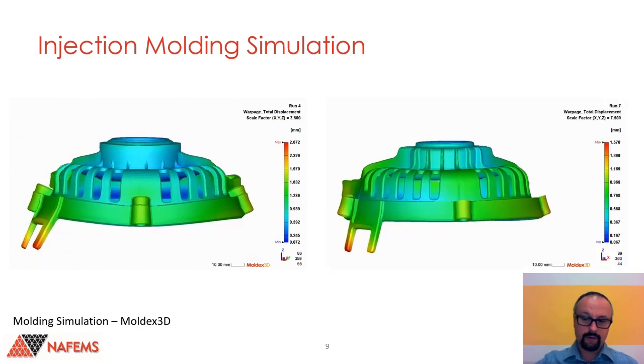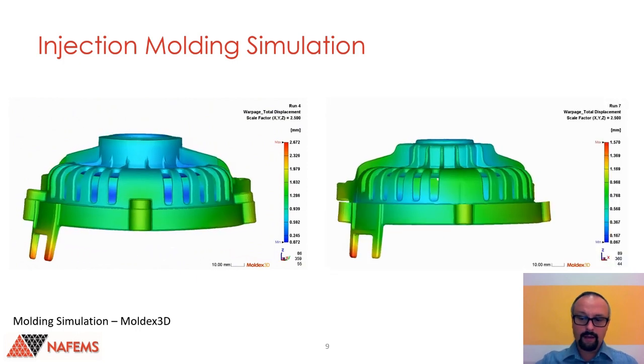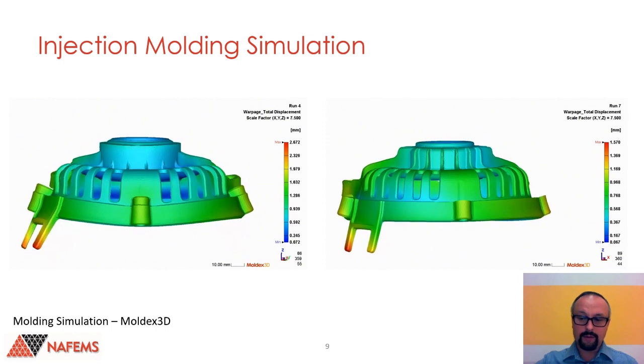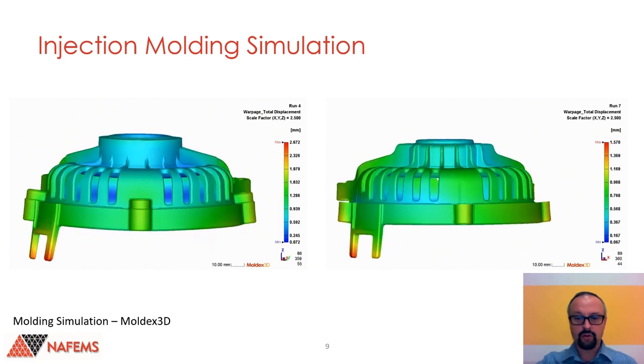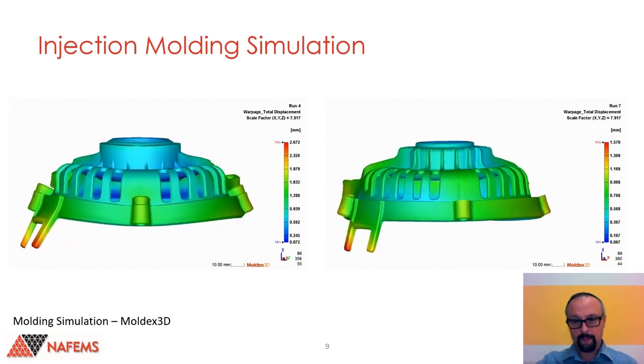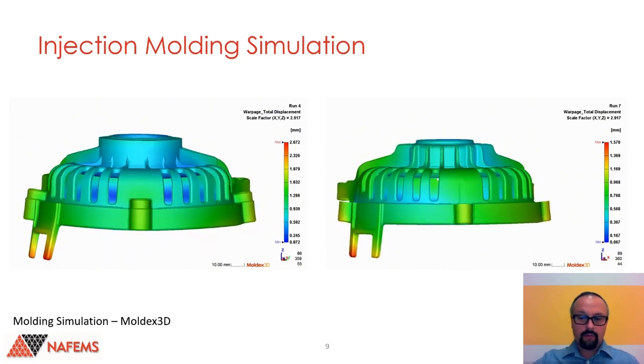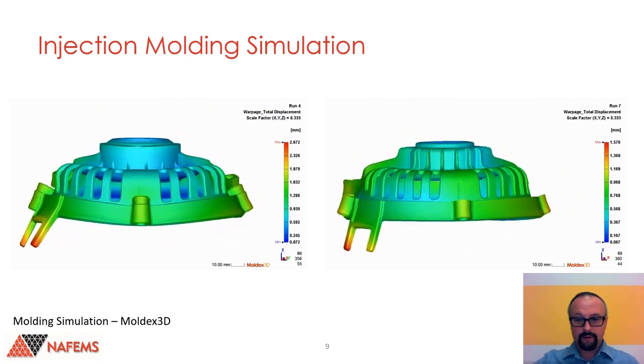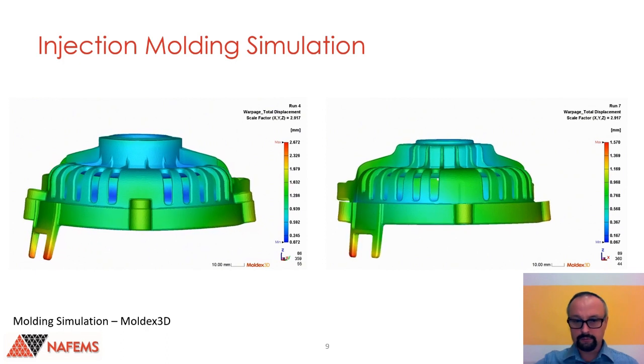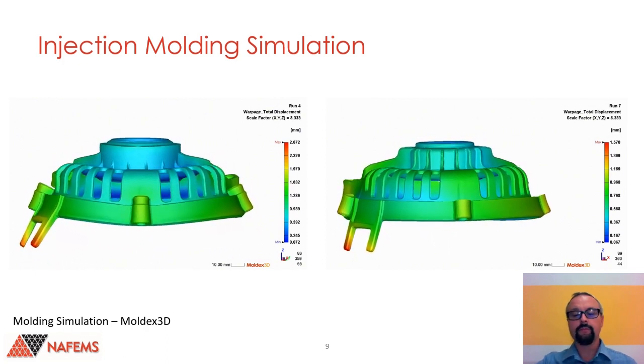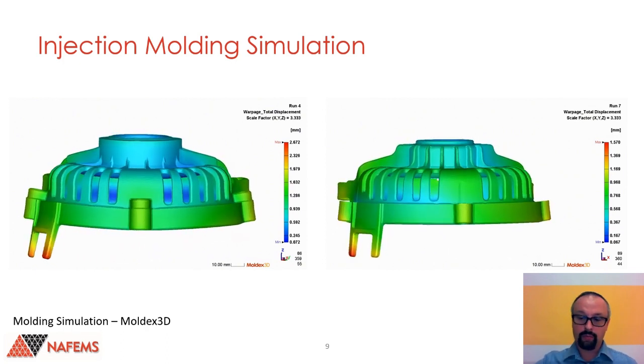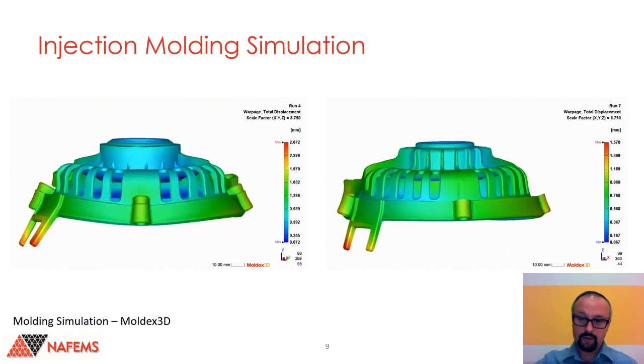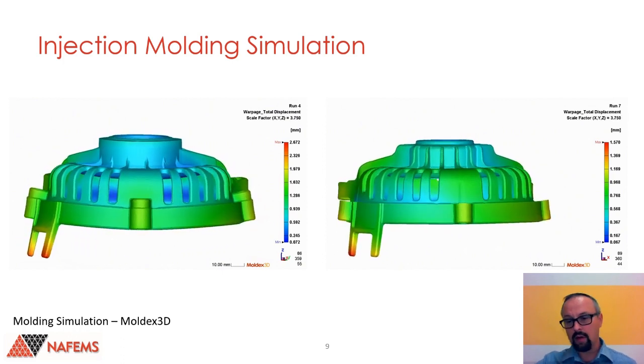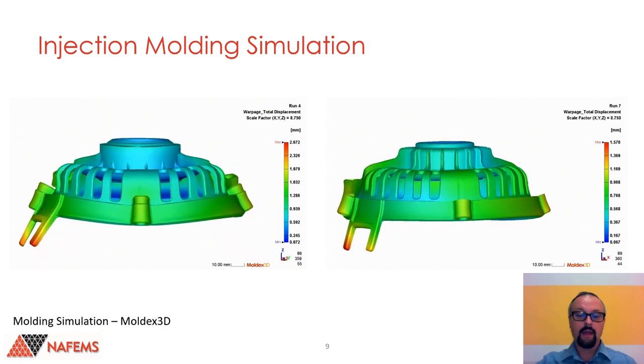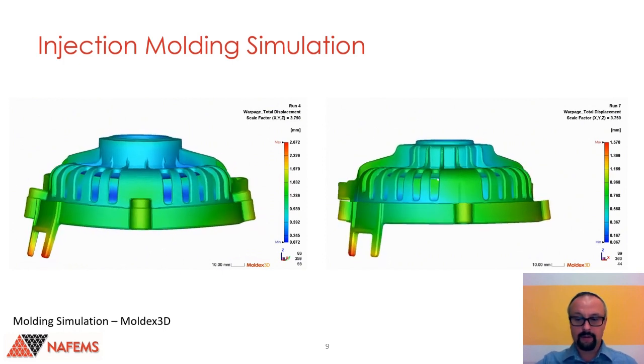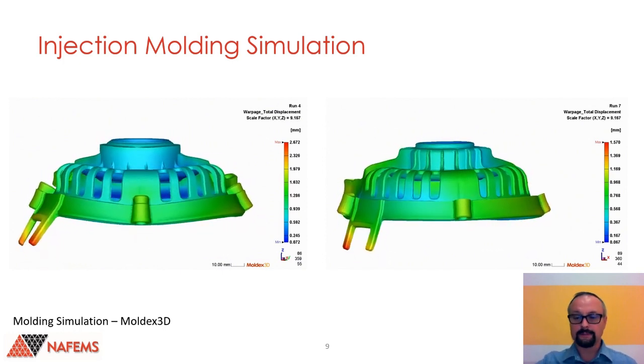And as you can see here, that's exactly what we did. By changing the geometry of the ribs in some areas near the bolts, we reduced the warpage almost by 50%, from 2.6 millimeters to 1.5, and keep it in the acceptable range.